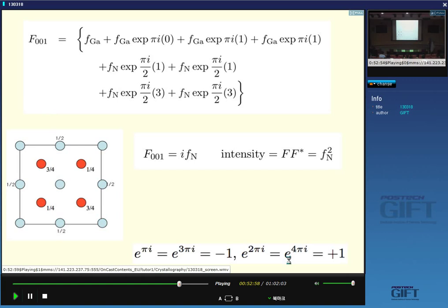Now the gallium terms, if I substitute for the 100 plane, this will come to 0, because look, it's 1 plus 1 minus 1 minus 1. And that's obvious, because for the gallium atoms at 100, we've got another set of gallium atoms in the middle, which will be out of phase.